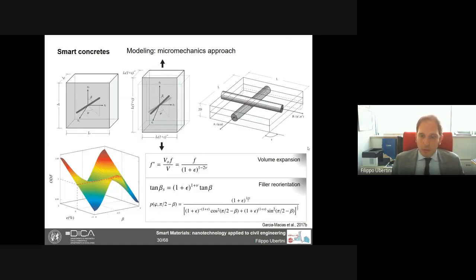Then how to consider the effects of strain? Well, when there is a strain, there is a change in volume. So there is a change in the volume fraction of the nanotubes, because of course the volume of the overall composite changes, but that's due to a change in the volume of the matrix, but the nanotubes do not change their volume really. Then we have the reorientation of the fillers, again, which we can analytically model.